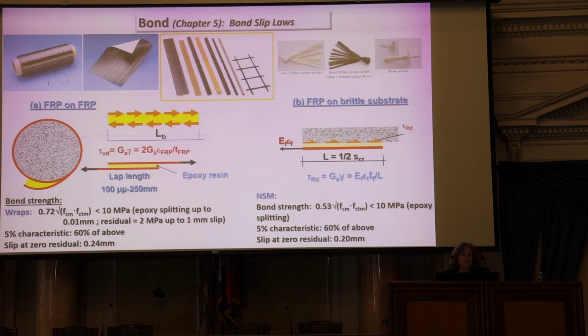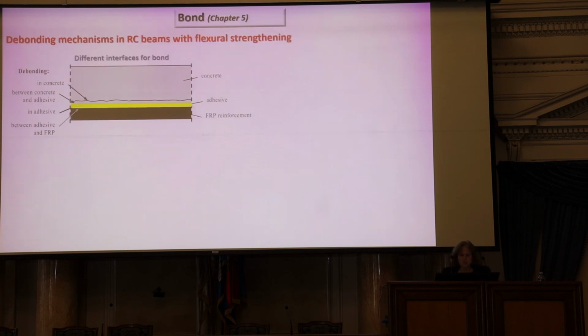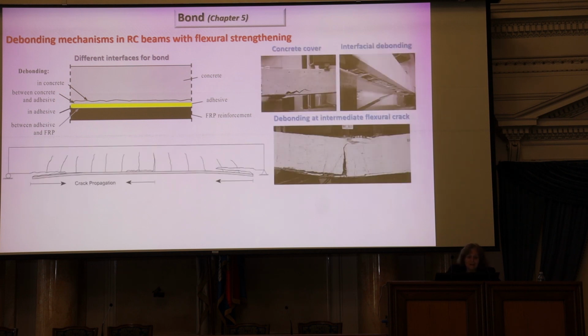The reason why you need this bond strength is because you need to be able, not just bond strength, you also get the slippage at zero residual bond. The reason you need this is because that quantifies the fracture energy of the substrate on which the FRP is glued on, and that fracture energy enters the calculations for the development length. So, this is the typical situation where you have cracking inside the substrate. These are the typical conditions on site. The worst, the most vulnerable situations are situations, as I said, where you have a laminate glued on the cover of a structural component.